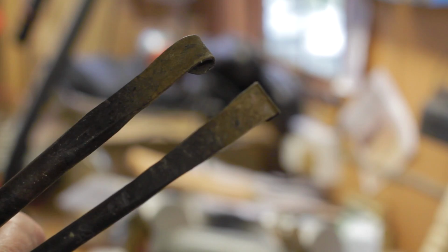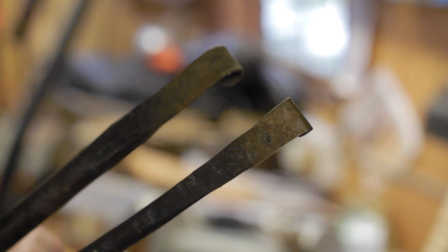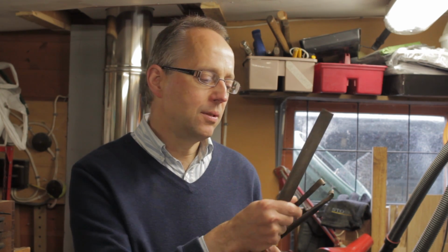Well, the tempering in the oven seems to have gone really well, because these have come out with a very nice straw colour, which is what I wanted. I did actually test these after the hardening, so that was when I quenched them in oil. And to test to see if they were really hard, I put a file on them, and the file literally bounced off. So the hardening's clearly worked well.